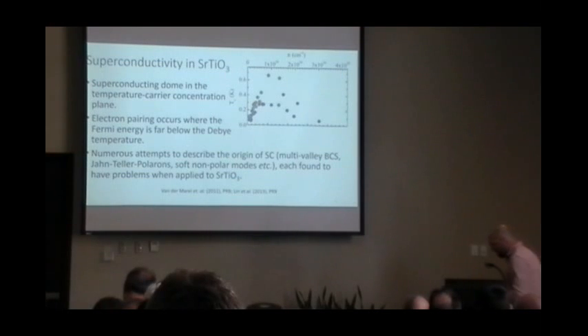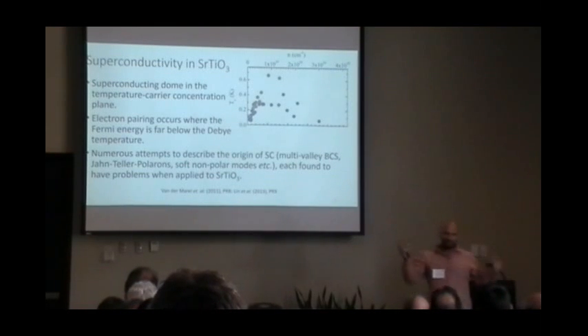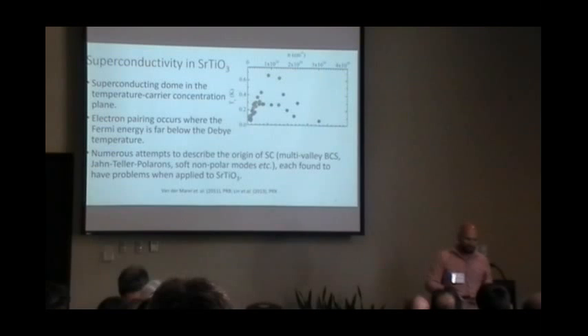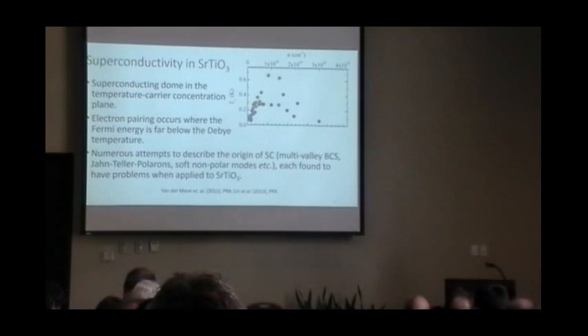Yes. I didn't talk about the other interpretations that you find in the literature, but there are people who have related it directly to the coupling of the transverse optical phonon modes. I can't remember right now what was the problem with that. It is in the Takala paper. But of course, in this case, it's very different. We do not couple to the transverse optical phonon, although it is related to the transverse optical phonon that goes to zero.